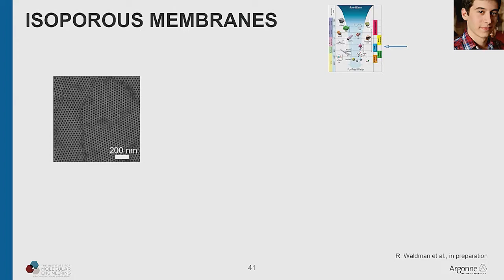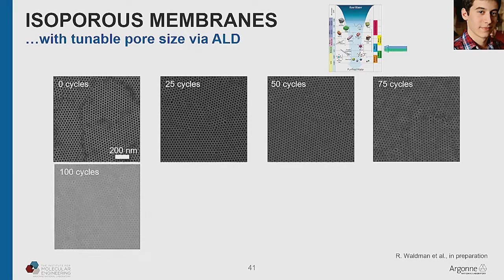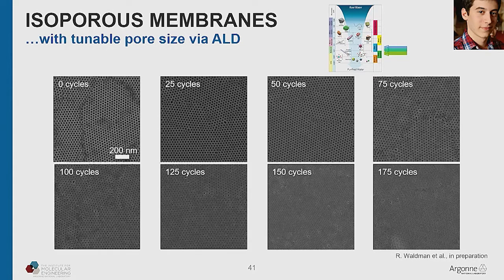Just to show you, you can, in fact, make such films. There's an SEM top view of one such film where you can see the pores all are more or less the same size. And the size here is in that range that is quite a challenge for commercial membranes, that sort of nanoscale size. What's cool then is we did SIS to make this. You can now turn to ALD and overcoat that membrane to tune down the pore size to be whatever you want with precision. And you can see that here. Just by increasing the number of ALD cycles, you just narrow down all those pores by the same amount. You could, in principle, close them all the way off, which we've almost done here. So this allows you to design a membrane where all the pores are the same size and they're all exactly the size that you want.